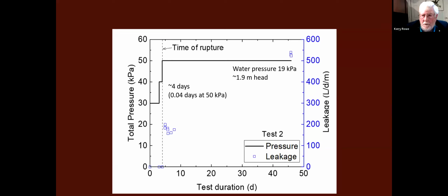Here is results from another test, and we started at 30 kilopascals. We sat there for a few days, 4 to be precise. Then we increased it fairly quickly up to 50 kilopascals, and we let the load sit there. And in fact, almost immediately, 0.04 of a day after increasing it from 40 to 50 kilopascals, we saw a failure. The leakage began at about 200 litres per day per metre and increased with time. When we decided to terminate the test after about 46 days, it was about 525 litres per day per metre of head. And this was under 1.9 metres of head, 19 kilopascals in round numbers.